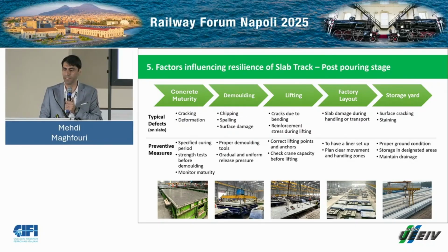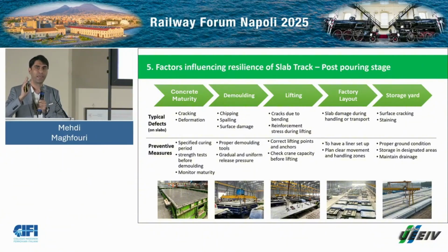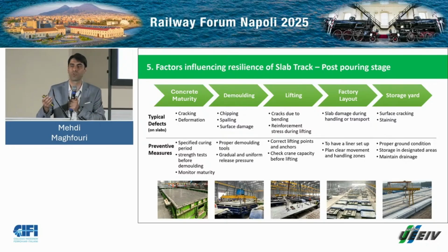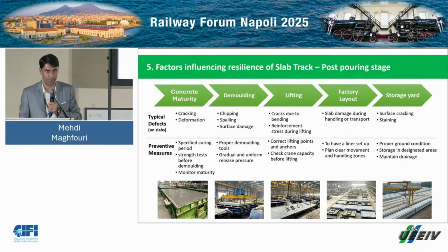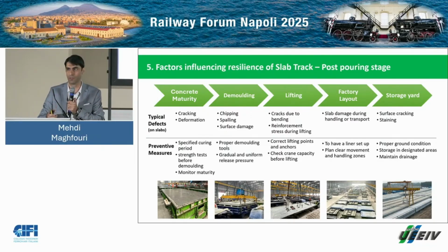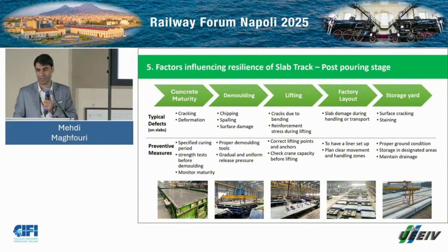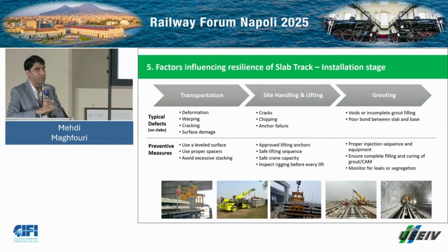And then lifting: some cracks and some defects can happen during the lifting, so correct lifting points and anchors are needed, and the crane capacity shall be checked before the lifting is carried out. The factory layout is very important because we don't want so much handling. The more handling, the more defects might happen. So it is strongly recommended to have a linear factory layout, and a storage yard, of course, should be leveled with a proper ground surface.